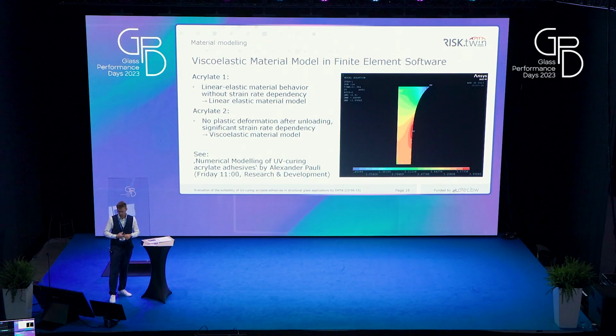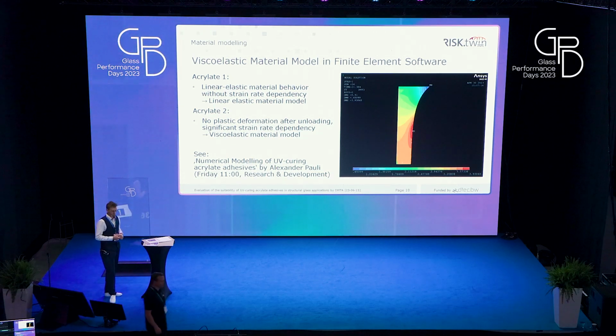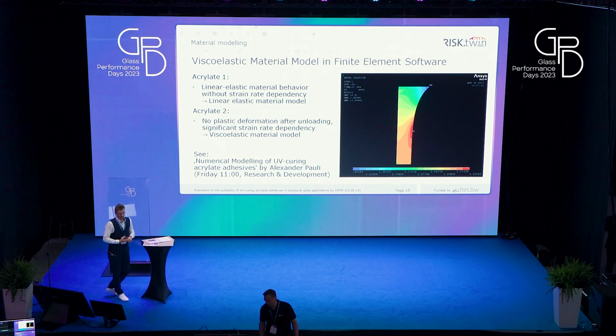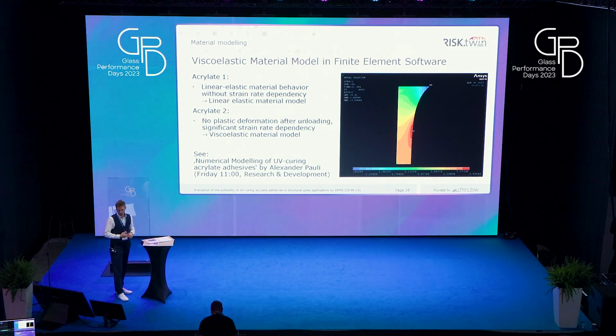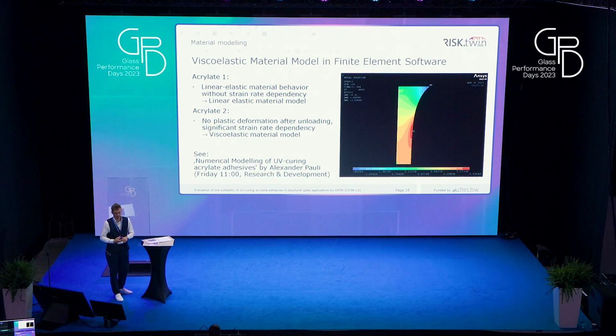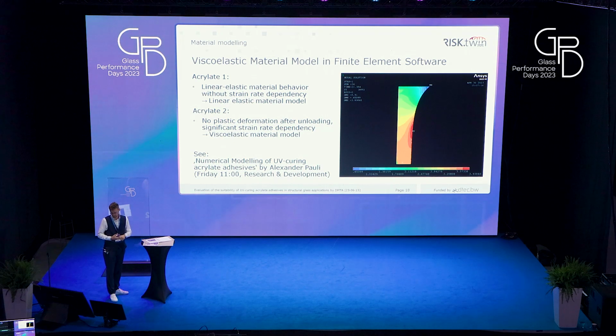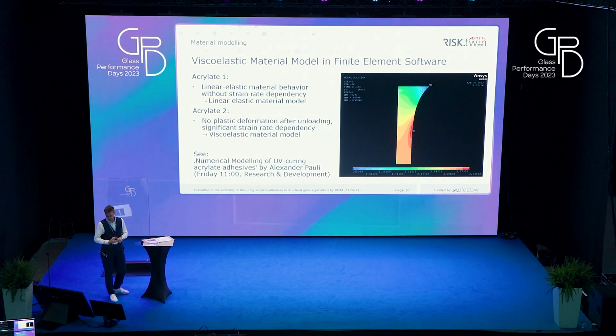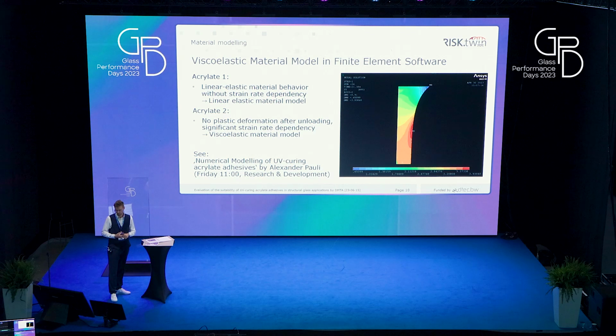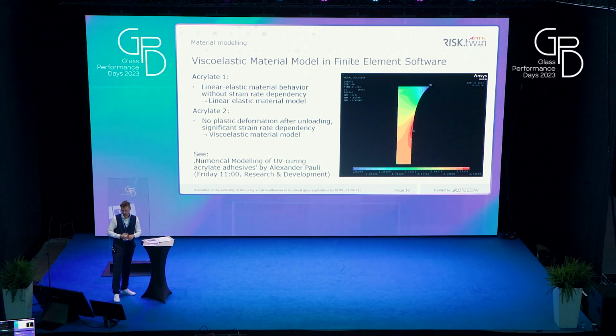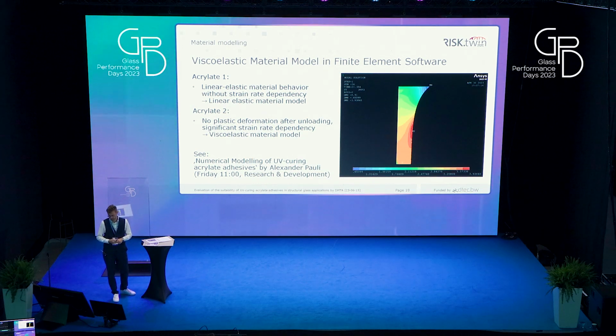Now, regarding the material modeling in finite element software, for our state of research for now, we model the Acrylate 1 with a linear elastic material model because of the results of the uniaxial tension tests. And Acrylate 2 shows a clearly viscoelastic material behavior. And it is important to mention that it shows no plastic deformation after unloading. So a viscoelastic material model is the right choice.